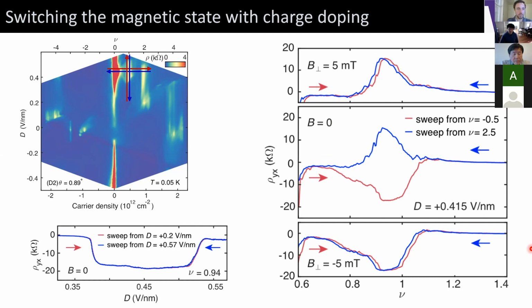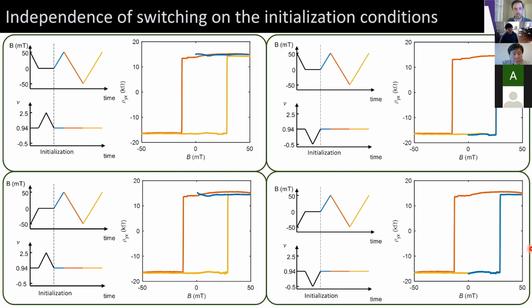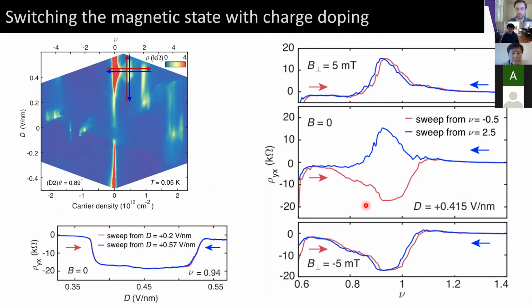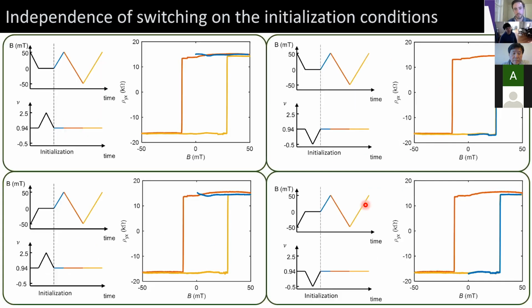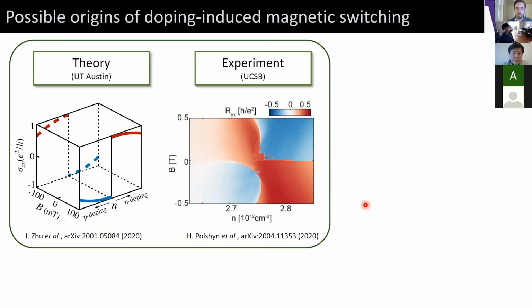I'm running short on time, so I'm not going to go through all the details, but you can ask me afterwards or believe me when I say that this does not seem to depend on initialization conditions. So for example, the history of which way we swept the magnetic field to get to 0 doesn't determine whether it chooses a positive or negative state. It really seems to be determined just by the direction of the doping that we sweep from. Okay, so what might explain this unusual phenomenon?